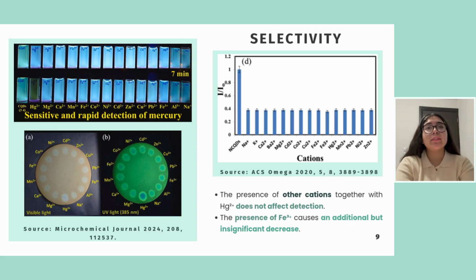Additionally, these authors evaluated the selectivity of carbon quantum dots toward different metal ions. Various cations were added to the fluorescent carbon quantum dot solution, and only the carbon quantum dot mercury-2 ion system exhibited a significant decrease in fluorescence intensity within the first 7 minutes of observation. This behavior demonstrated the high selectivity of carbon quantum dots for mercury-2 ion detection. Similarly, Teruel and collaborators reported that only iron-3 ion produced a slight decrease in fluorescence intensity, although this effect was negligible compared to that caused by mercury-2 ion. Therefore, they concluded that nitrogen-doped carbon quantum dots can serve as selective fluorescence probes for mercury detection in aqueous solution.